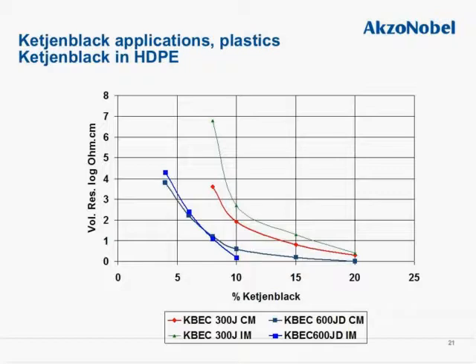And we have a comparison of Ketjenblack 300J and Ketjenblack EC-600JD in HDPE, both compression molding and injection molding. So as you can tell from this graph, there is a little bit of difference whether there is a compression molding process or injection molding. Everything else stays the same. It is the exact same concentration of Ketjenblack, the exact same polymer matrix, and no other additives. But injection molding can induce orientation not only of the polymer chain but also of the particulate aggregates. At the same time, the compression molding is actually freezing everything in place. So there is a slight difference in terms of measured resistivity and conductivity.